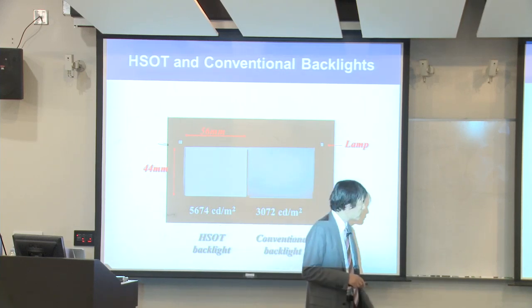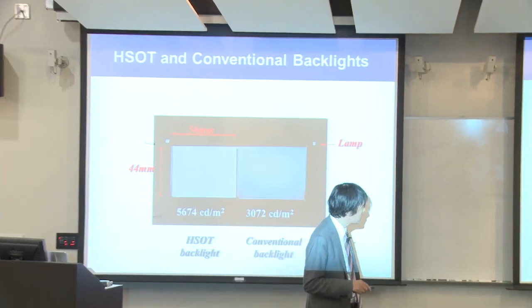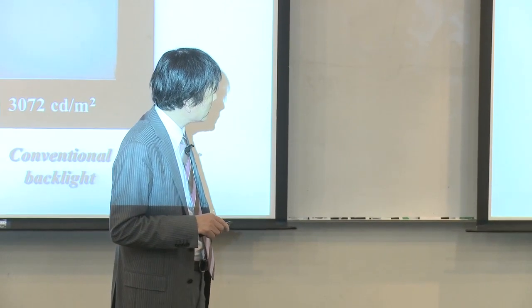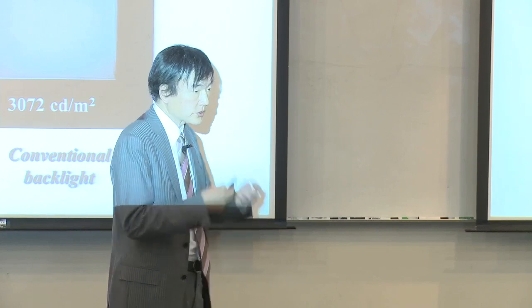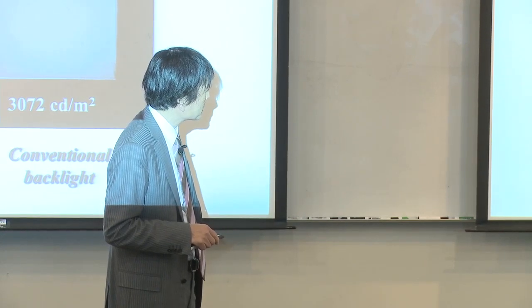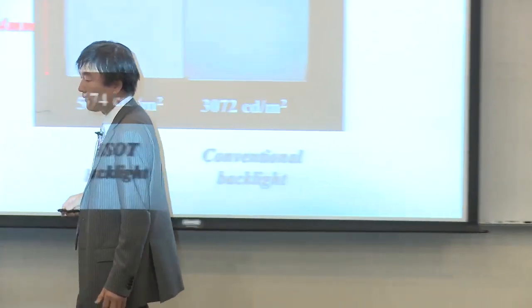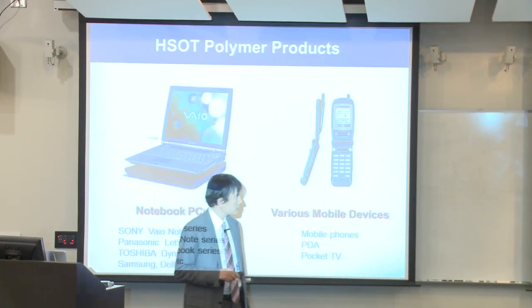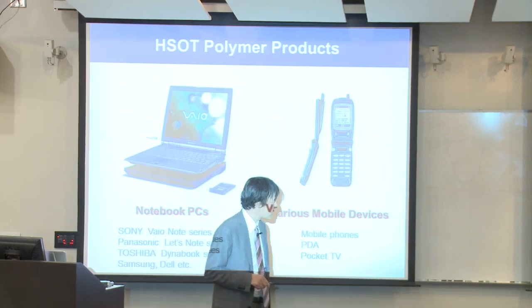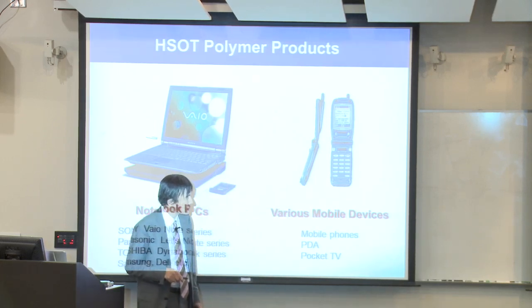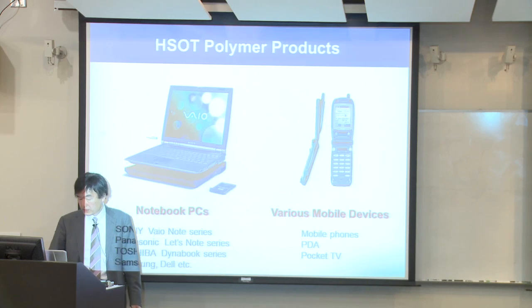And this is a comparison of the luminance. In the case of the conventional transparent backlight, the luminance is 3,000 candela, but with using the HSOT polymer, utilizing the scattering, the intensity is 5,700. It's almost double the intensity of the conventional backlight. So our HSOT polymer has been used in the Sony Vaio, Panasonic, Toshiba Dynabook, Samsung, and mobile devices.